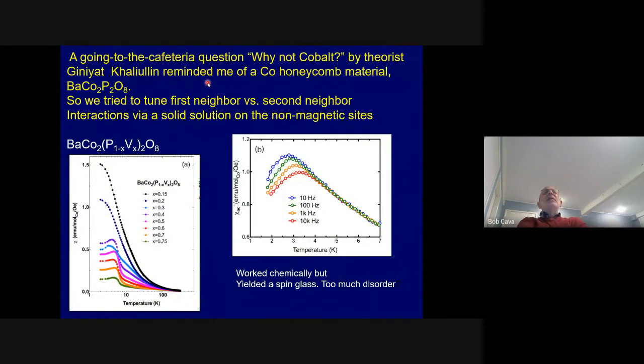You know, it matters a lot. I'm sorry that the world changed. I hope it goes back, but it matters a lot to just talk to people informally. And this theorist, Khaliullin, stopped me on the way to a cafeteria one time and said, well, what about cobalt? And cobalt is a bizarre element in the periodic table. So it's a 3D element, so it should have only spin contribution to the effect of magnetic moment. But in every single compound that is known with cobalt, as far as I know, the moment is too big. So no matter how you count the unpaired electrons on cobalt, whether it's high spin or low spin cobalt, you have to have a significant orbital contribution to the magnetic moment, which means that there has to be spin orbit coupling in the system. So cobalt is a brilliant observation by this theorist.